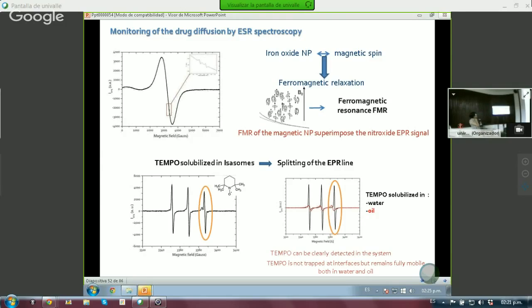As you can see in the first plot, all it's showing is that the ESR spectroscopy showed that the ferromagnetic relaxation is visible. So you see here, there is this spot that we highlighted, which is developed in the inset. And as you can see, we can obtain the signals of the magnetic nanoparticles, and on top of them, we have the signal related to the nitroxide. And what is the most interesting result is the bottom two figures.